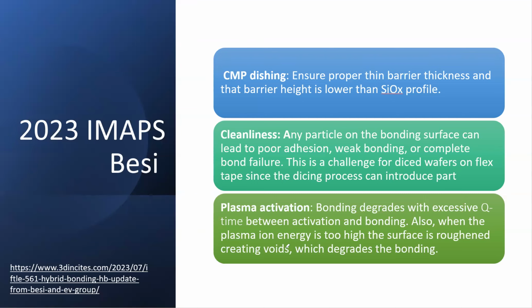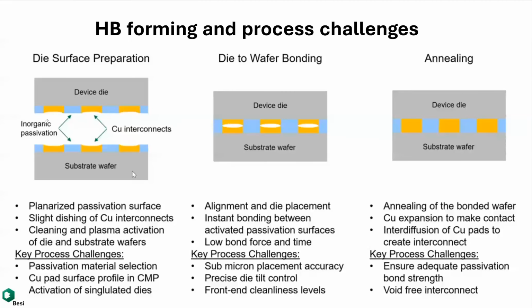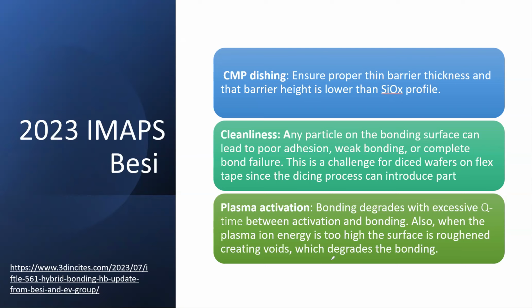But if you do too much, say the process is bombarded with some kind of plasma, and the plasma activates the surface, it cleans and activates at the same time, pretty nice. But if you do too much, it will rot. The surface becomes rough. Okay, it kills the surface. In that sense, you've got problems. You degrade, you create voids. It roughens the surface and then degrades the bonding. So these are the current process challenges that face the big vendors, the big tool suppliers. I just want to give you a high level feeling of that.